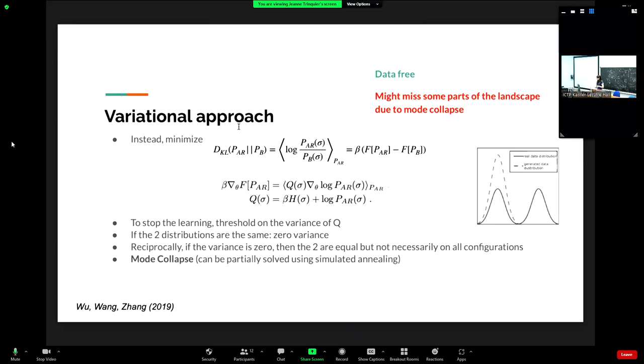You can write this Kullback-Leibler divergence as a difference of free energy, and you can compute its gradient. To do the learning, you have a first guess for your autoregressive model. You take a first sample of this model, estimate the divergence and its gradients, and update the model. You stop the learning when you are below a certain threshold on the variance of Q, which is here. Q is beta times the energy plus the log of the probability of your model.